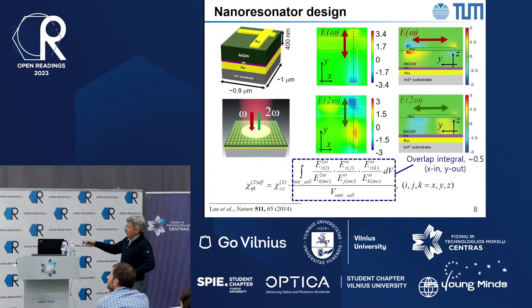So you can see that this antenna was designed so that at the fundamental frequency, which in this case was 10 microns, there was some field enhancement at the ends of the antenna. And at second harmonic generation with this polarization, there was this field enhancement on that antenna. And this is the cross section of the field along these dashed lines. So you get an idea of how the field is enhanced.